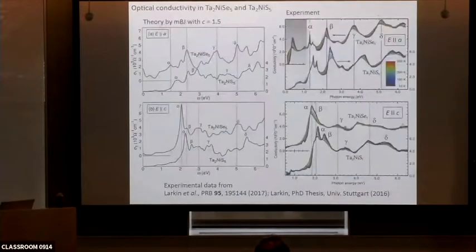And this is the calculated optical conductivity. This is the theory result, and these are the corresponding experimental results. With the electric field parallel to the A direction, we found these peaks. It's perpendicular to the chain electric field. We have an alpha peak here, a beta shoulder here, and a gamma peak around 3 electron volts. We have a peak here, and a delta peak here. And also we have alpha peak, beta peak, gamma peak, and delta.